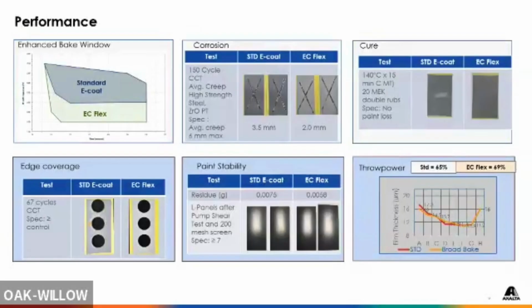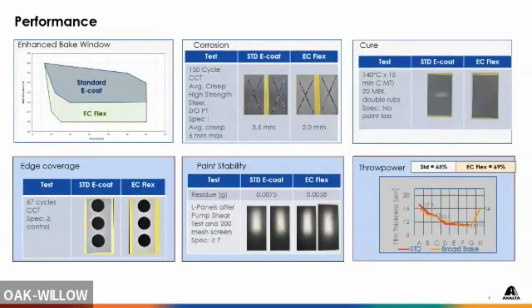During the electrodeposition process, we're able to coat that very nicely, but then when it gets in the oven, due to the film flow and the cross-linking, some of that coating will pull away from the edge, and that's our first place where we see corrosion. So some of our customers ask us to enhance the edge coverage.